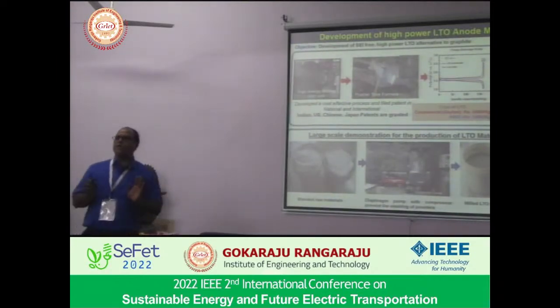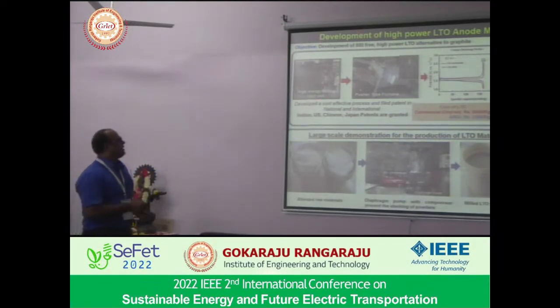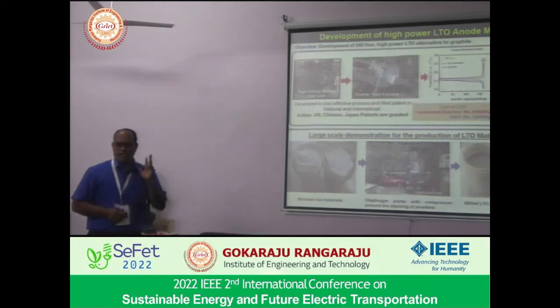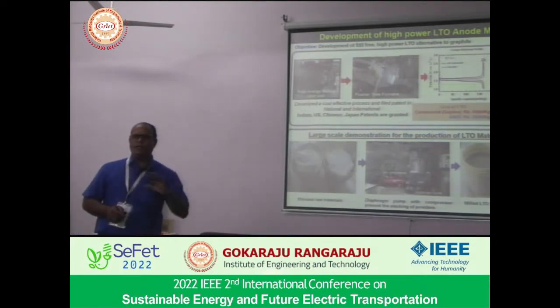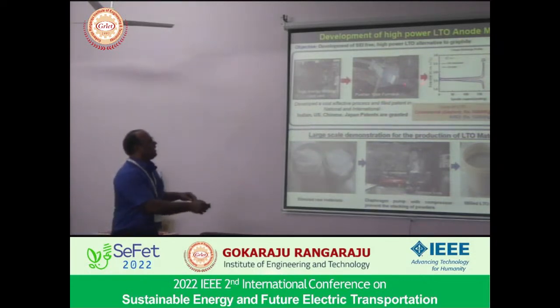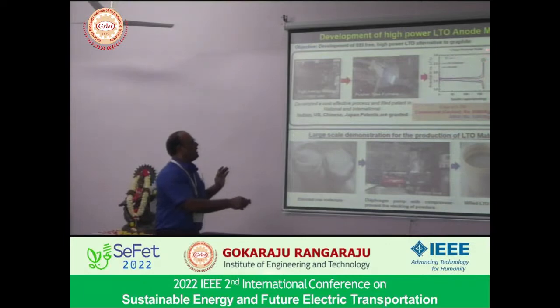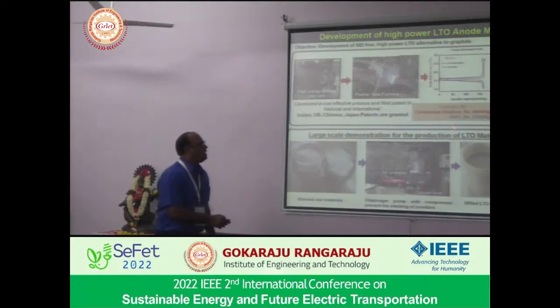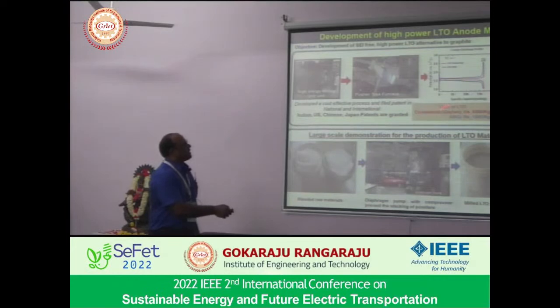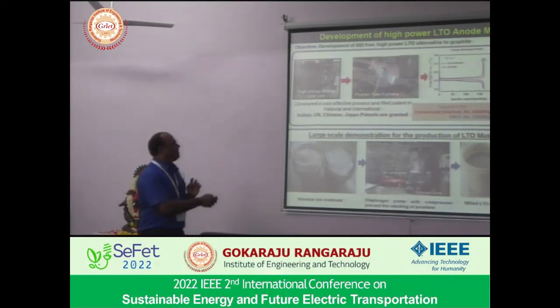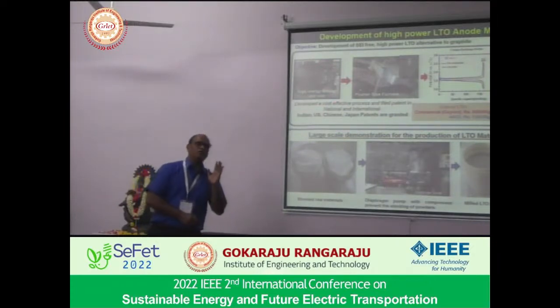A similar solid state process we have adopted for lithium titanate as well. Here, this is the high energy milling unit we initially used, with a capacity of 2 kg per batch. We simply used a lithium precursor and a titanium precursor, milled at around 500 RPM, and then subsequently heated, giving a kind of carbon coated lithium titanate. If you can see the performance of the material developed by ARCI, it is almost close to the commercial material. These are the morphologies of the commercial as well as ARCI LTO. It is 100 to 250 nanometer size particles, whereas the commercial LTO is in the range of 100 to 150 nanometers. But when we estimate the production cost, the commercial cost comes to 5,000 rupees per kg, whereas when we synthesize using the solid state process, we end up at only 1,200 per kg.